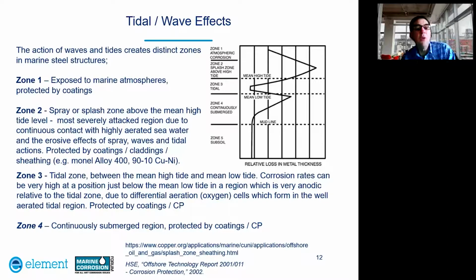Zone 3 is a tidal zone, between the mean high tide and the mean low tide. The corrosion rates can be very high at a position just below the mean low tide, in a region which is very anodic relative to the tidal zone. This is due to differential aeration cells which form in the well aerated tidal region. In this region, the steel would need to be protected by coatings and cathodic protection. In zone 4, which is continuously submerged, the steel would be protected by coatings and CP.